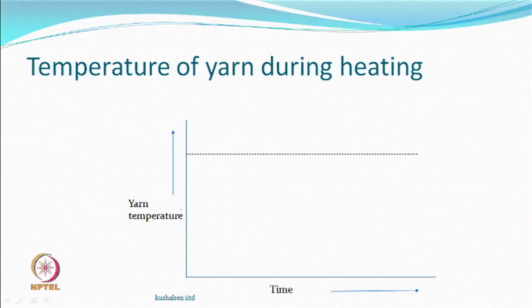We know that the yarn is at room temperature when it enters the machine. The bond breaking can take place only if the yarn has achieved a certain temperature. So the time of texturing would have to account for the time taken to raise the temperature of the yarn from room temperature to the required temperature, after which all these rearrangements can occur. The time required even to raise the temperature is going to be interesting.